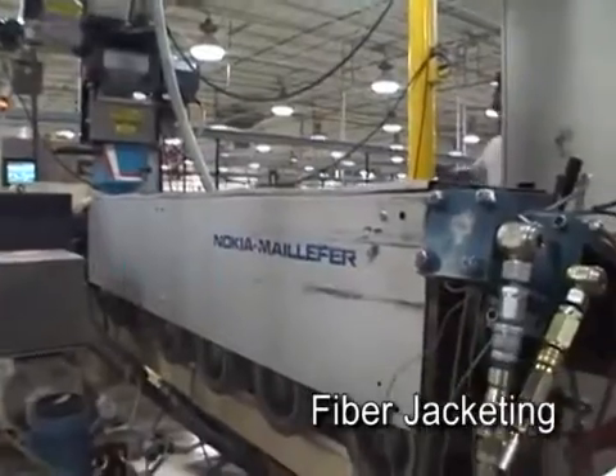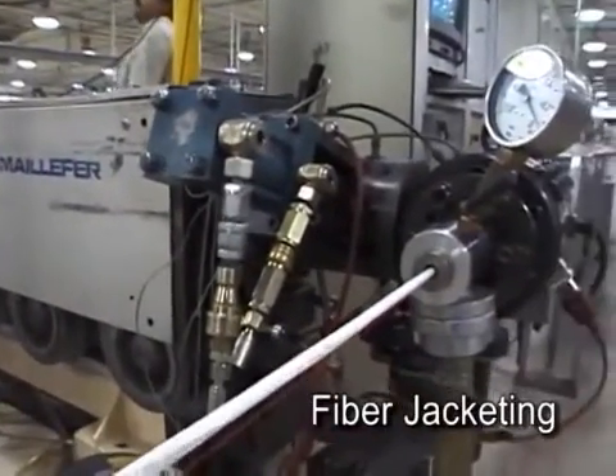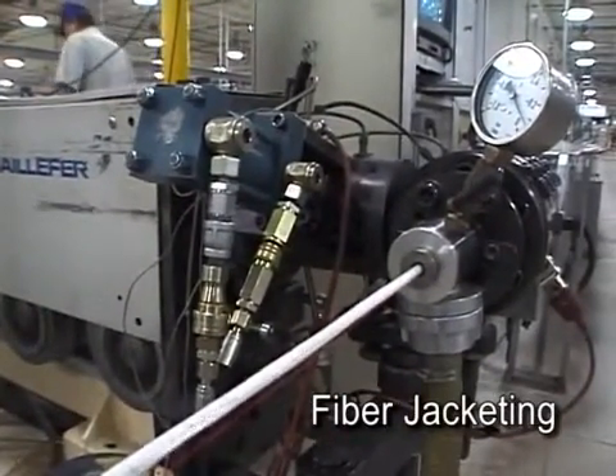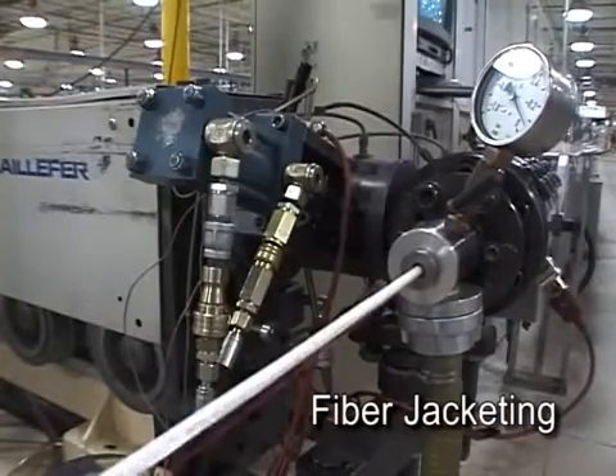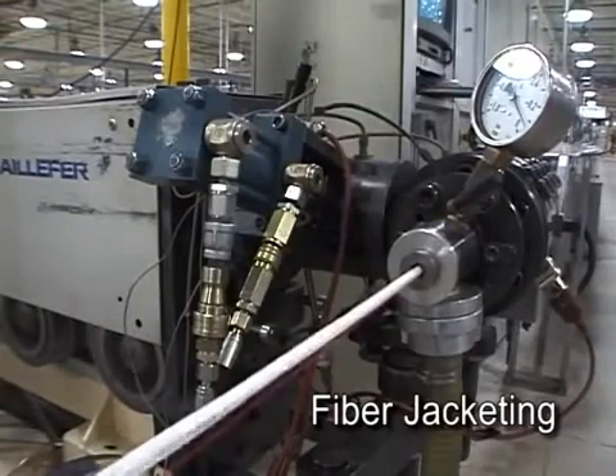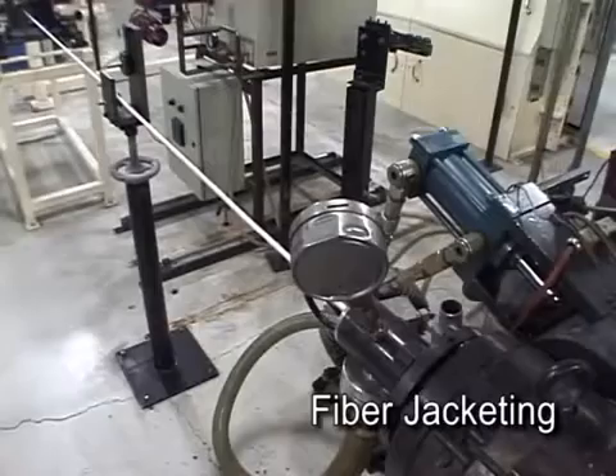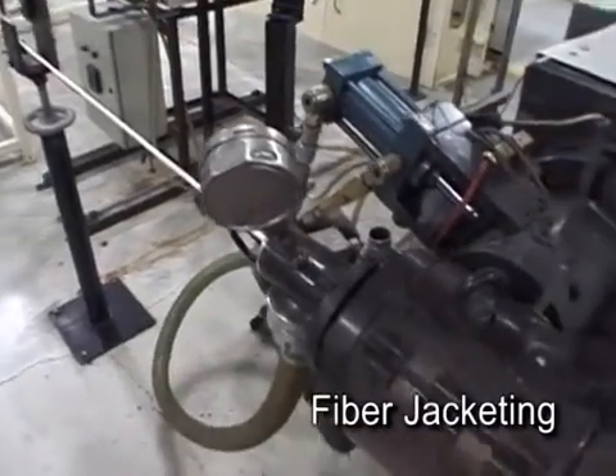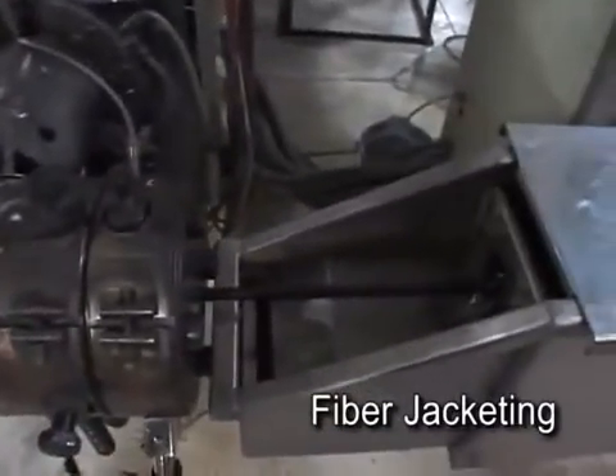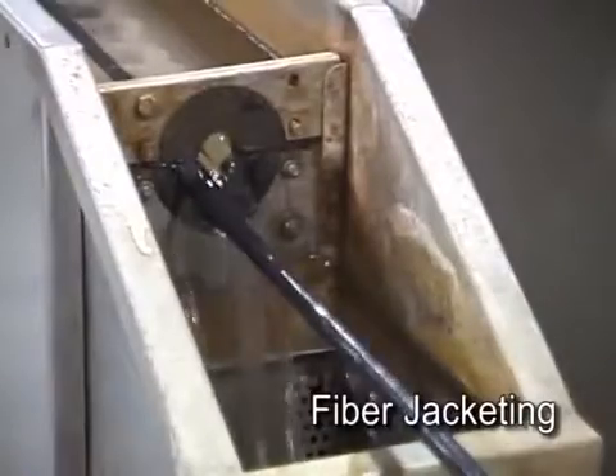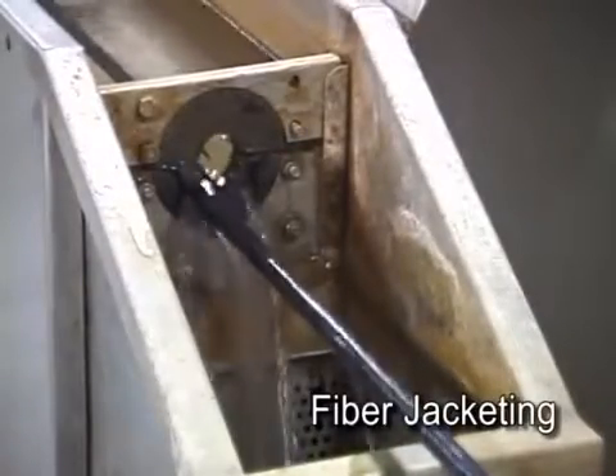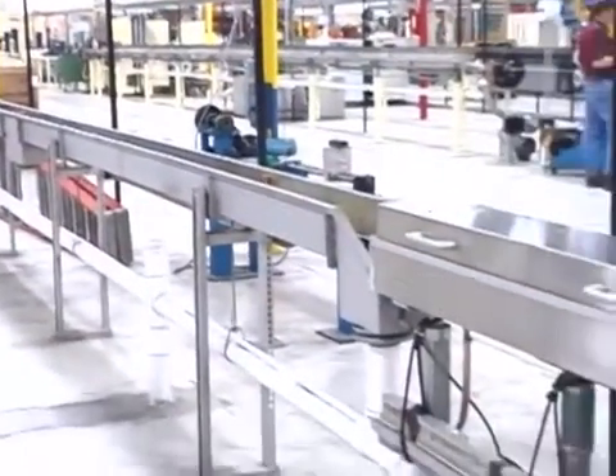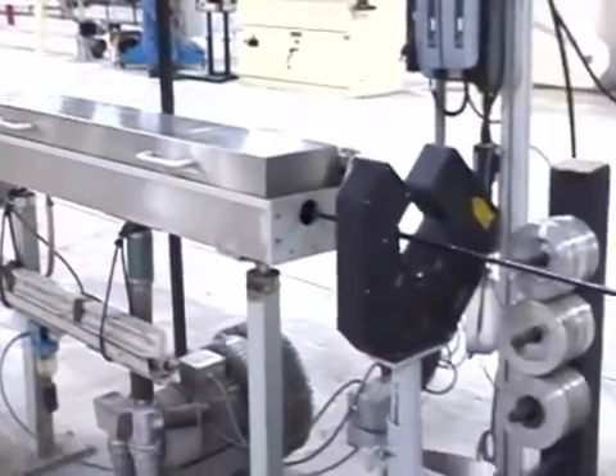The jacket extruder is simply a scaled-up version of the tube extruders we saw earlier. Molten jacket material is injected at high pressure and formed around the moving cable. When the cable leaves the extruder, it is very hot and quite soft, so it must pass through a long cooling bath while being kept straight to prevent the cable from developing a permanent curl. When the cable exits the cooling bath, it is passed through an optical micrometer to verify that its diameter is within specifications.